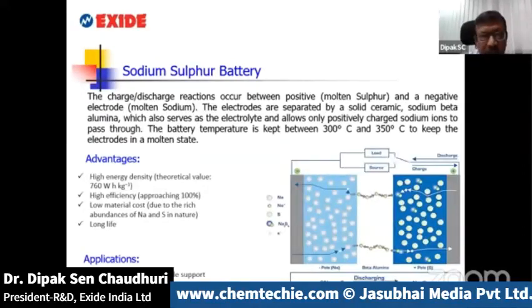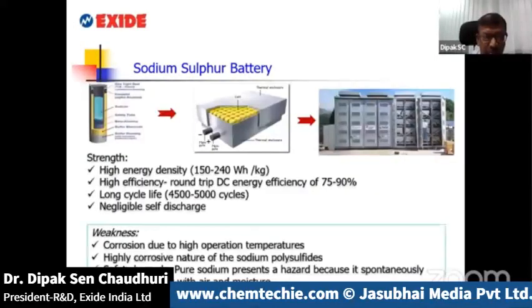Sodium sulfur is a technology which some of you might be familiar with, where we are talking of bulk storage of 30, 40, 50 megawatt hours, where there are certain vulnerabilities because this is a very high temperature application where the electrolyte or the battery has to be kept at temperatures as high as 300 to 350 degrees. But under that circumstance, it's an extremely robust system with a very high efficiency, as well as very low self-discharge and other features.